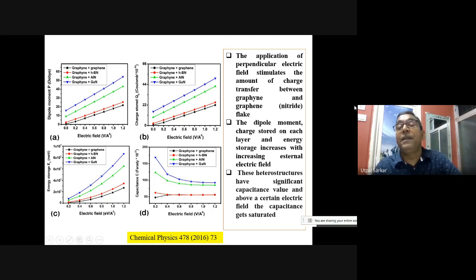So the application of a perpendicular electric field stimulates the amount of charge transfer between the graphene layers. The dipole moment, the charge storage on each layer, and the energy storage increase with the increasing field, but the nature is different. You see here quadratic, here it is linear. The heterostructure has sufficient capacitance value, and above a certain electric field, the capacitance gets saturated. That is clearly visible here, because there are no more polarizations to occur. That's why.